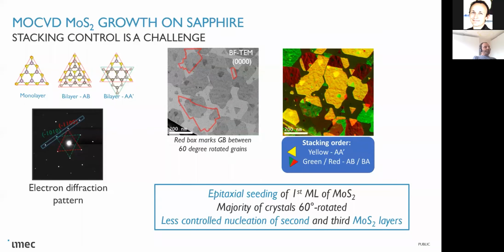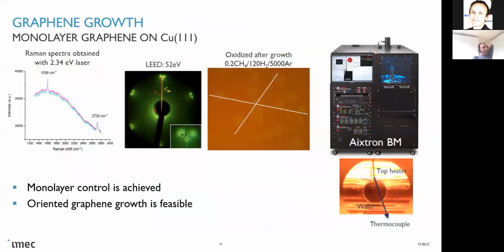So we believe that now these things are engineering problems, and basically for graphene, you can also achieve that if you make a single crystalline template. For example, in this case, it's copper 111, but we did it for platinum 111 too. There is a window to have oriented growth. And if you have oriented growth, you can close these layers, forming almost fully single crystalline graphene at wafer level.